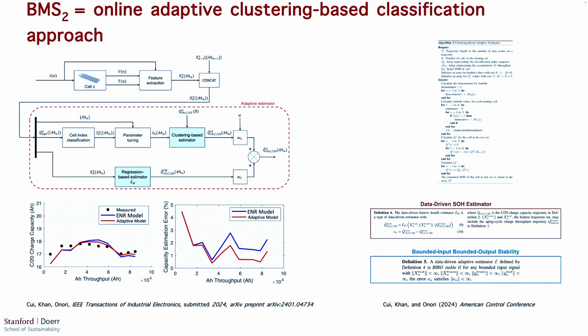So our approach looks at developing offline state of health estimation first, using machine learning models and a pipeline that we developed to clean, filter, and process the data. We tested different types of models, and we ended up using the elastic net regression model. That model was the base of our BMS2. Once those batteries are deployed in the field, they are equipped with this offline machine learning model, but as new measurements come in, the new measurements need to be processed in a way that gives us a guarantee of the state of health estimate.